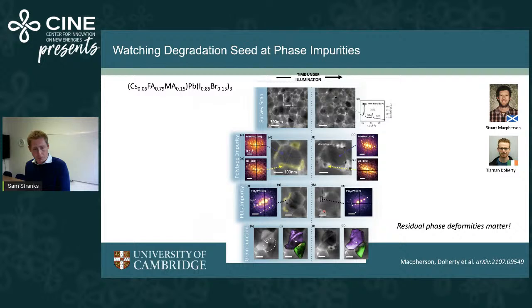And finally, this is an example where we have this hexagonal polytype sitting between two perovskite grains. So it's quite a small region here. And you can see, again, we see material loss at that site and metallic lead forming. But interestingly, the perovskite grain is shaded in green, we're also starting to see now that this starts to eat away at the perovskite grain as well.